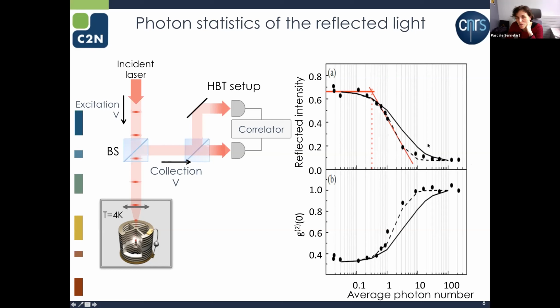And what is remarkable on this curve, I'm sorry, I forgot to put the reference here. This was published in 2017 in Nature Nanotechnology. You see that the threshold occurs below 1 photon on average. So we have less than 1 photon on average sent on our device, and suddenly it behaves like a non-linear system. And if you look at the statistics of the light that is reflected, when you saturate the transition, there is no longer the quantum dot effect. So you end up with a G2 of 1. Just for specialists, that is what characterizes laser light, a coherent state of light. And when we are at low power, where the quantum dot reflects most of the light, you see that the G2 is around 0.3.